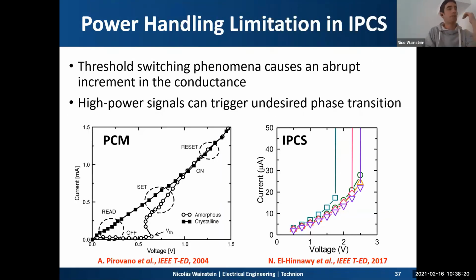But before that, I mentioned that one of the limitations of the IPCS is the power handling capability, which is limited by the threshold switching, or Ovshinsky threshold switching, phenomenon, where the resistance of the PCM in the amorphous phase is suddenly reduced when the voltage exceeds a certain value, the threshold voltage. Though this is the phenomenon that allows the PCM to work as a two-terminal memory device, in the IPCS it can trigger an unintentional phase transition when the RF signal surpasses a certain power level. And since the threshold voltage is determined by the dimensions of the PCM, in the IPCS this threshold voltage will usually be much higher than in two-terminal devices, but still it limits the maximum power that we can apply to the switches.